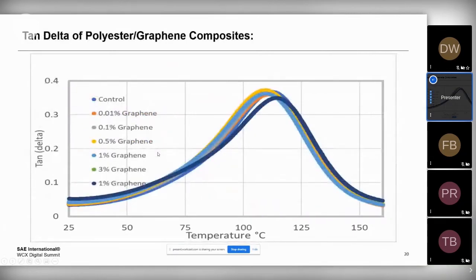Now, the impact it has upon the glass transition temperature is not really huge. It only stays within a few degrees. So that tells us that it's not really changing the crosslink density all that much. It's behaving relatively stable. But the interesting thing is, if you increase your graphene concentration, you can eventually get to a point where it will increase the Tg simply as a function of space between the molecules and their ability to move.